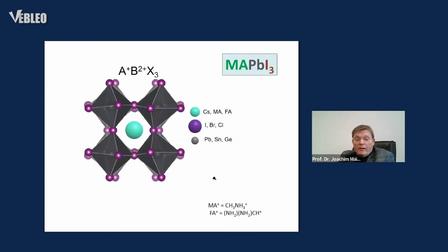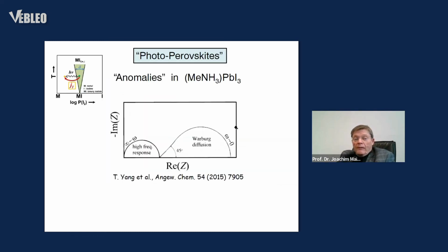It's perovskite, and in the middle of it you typically have organic cations such as methylammonium or formamidine. And unlike the usual perovskites where the anion is an oxide ion, here we are dealing with halogens. I'll only mention 2 points. One is, again, the charge carriers, electronic and ionic, are to the fore.